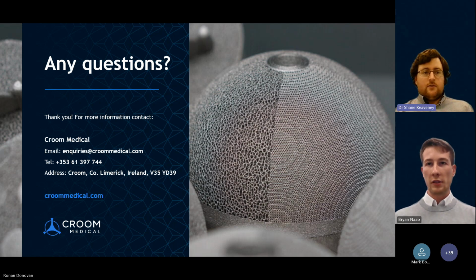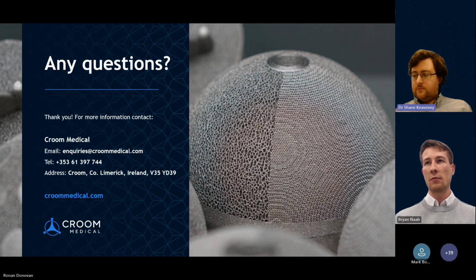Yeah. So defect sizes vary, of course, depending on the process. Generally, if you're talking about gas defects, gas pores, they would be on the order of 2 to 20 microns, so relatively small. If you're talking about lack of fusion defects, they can actually get quite large, and obviously the larger they are, the more detrimental they are. And the critical thing about lack of fusion defects is their irregular shape, which leads to more stress concentration around that defect. There's a number of metrics you can apply to these defects, such as the sphericity. Generally, the more spherical they are, the less detrimental they will be. So if you've got a low sphericity, you know that defect's going to be quite critical.